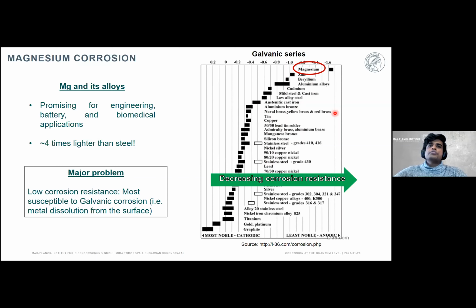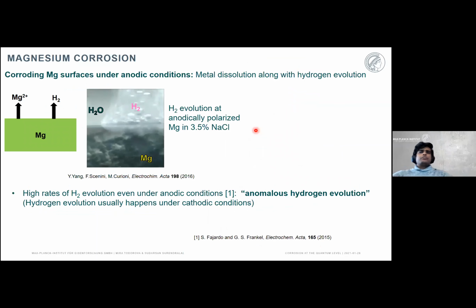It is easily the most corrosive of all engineering metals. What's very peculiar about corrosion of magnesium is that not only do you see metal corrosion when you polarize it anodically, you also see the evolution of hydrogen from magnesium under anodic conditions. That's what you can see in this movie, where you see hydrogen bubbles coming out of a magnesium surface in an aqueous solution. This is quite puzzling, and this is known as anomalous hydrogen evolution, because hydrogen evolution is an electron-consuming reaction, like Mira has mentioned earlier. However, this happens under anodic conditions where there is a deficiency of electrons in the metal.